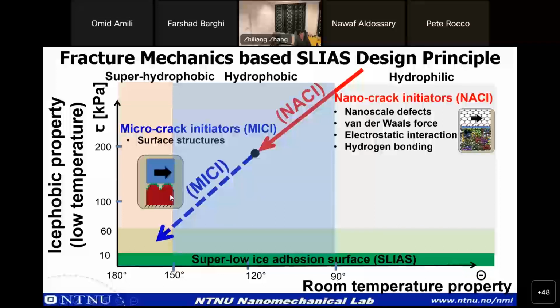However, you know, water in many cases can wet the surface, even the roughness. So once we have wetting at the valley, then when we have interlocking, ice adhesion will increase rather than decrease. So this MICI approach is not stable. We have been asking ourselves, do we really have to go through this MICI path? Can we go another path? For example, can we go down directly from anywhere to the super low ice adhesion surface region? From here?